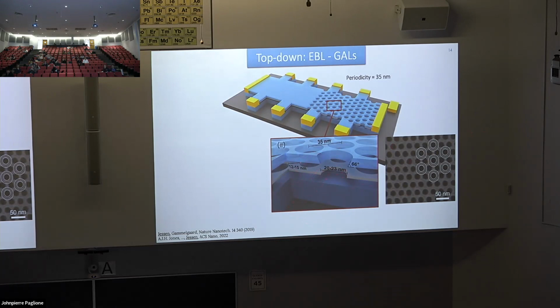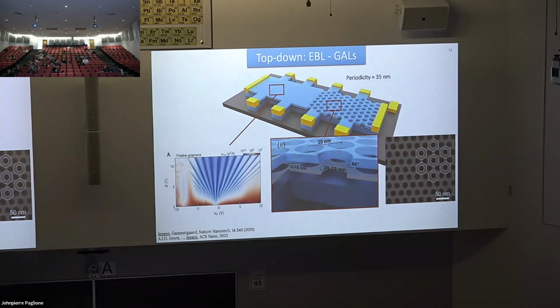There's some graphite on top. And we were able to make fairly small holes into the top boron nitride and then etch that into the graphene. This is an SEM image of an actual sample. Periodicity is something like 35 nanometers. If you look in the part of the graphene where we didn't make any holes, you see these straight lines. Everything looks more or less typical as it should. We accidentally had some Moiré physics going on, but just pretend like that didn't happen.